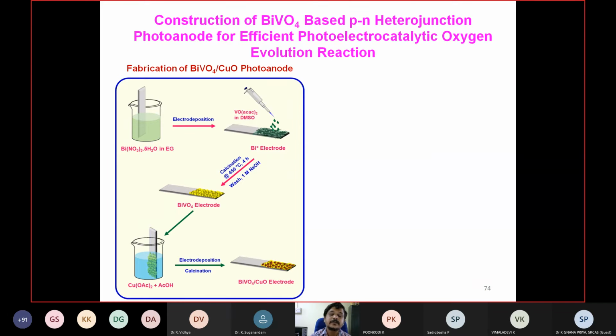So the bismuth nanoparticles are formed over the surface. Then we have added vanadyl acetylacetonate solution over the surface. Subject to calcination, it forms bismuth vanadate. Again, we have taken the copper oxide precursors, then we did the electrodeposition. Finally, we got the bismuth vanadate and copper oxide electrode.